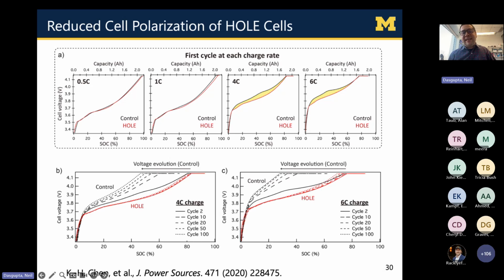And we can see after extended cycling of 100 4C or 6C charges, we see a lot of voltage fade. We see a lot of power fade in our cell, where the voltage is increasing very rapidly after 20, 30, 50 fast charge cycles in the control, whereas we see a very stable voltage profile after hundreds of 6C fast charging cycles when we've introduced this hole pattern.